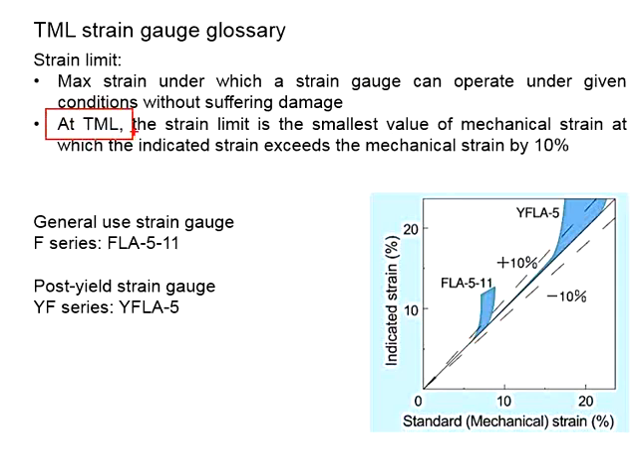Now, based on the definition of TML, the limit was set at 10% variation. So, by the time the line here touches the 10%, this will be the limit for the strain gauge. And this limit is known as the strain limit. We have another type of strain gauge. This type can give you quite good measurements until here, and then the variations enlarge. By the time the curve hits this 10% limit line, that will be the limit of this strain gauge. Now, if you look at these two types of strain gauge, the difference is their limits. This one is less than 10%, and this one is more than 10% but less than 20% mechanical strain.